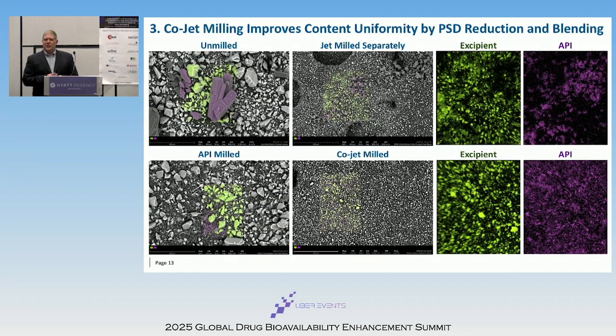I'm just going to go over this really quick, just because the images are cool. This is spiral jet milling and how it can improve content uniformity by particle size reduction, as well as blending. So on the top left is unmilled material, unmilled API. We distinguish the two by using SEM and an EDS detector. So the green material is just silicon dioxide, and then the API is purple, it's HCl salt. So those are 2 elemental signatures, silicon and chloride.